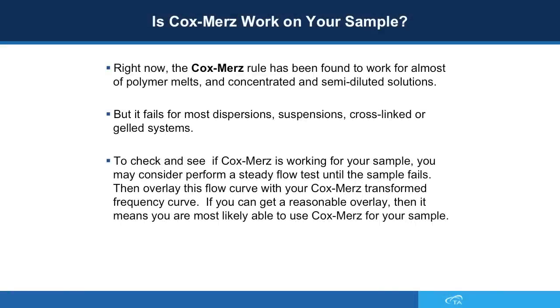The Cox-Merz rule has been found to work for most polymer melts and concentrated semi-diluted solutions. But it fails for most dispersions, suspensions, and cross-linked or gelled systems.